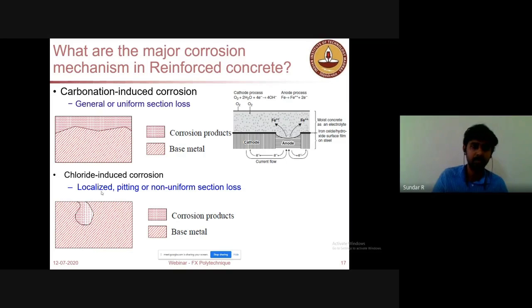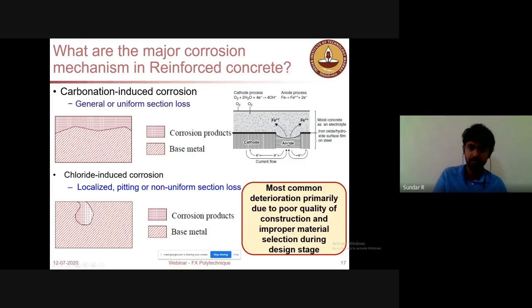However, in carbonation, the corrosion mass loss will be uniform, so there will be sufficient warning before the failure. In pre-stressed concrete and so on, chloride-induced corrosion can be so catastrophic that it may lead to sudden failure. Pre-stressed concrete can come down suddenly if the strands inside the concrete were affected by chloride-induced corrosion. Here you could see the anode is the steel member, and there will be a cathode, which is a portion that is not corroded, and due to this electrolyte concrete, the corrosion is happening. This is a very common problem that you will be seeing everywhere.